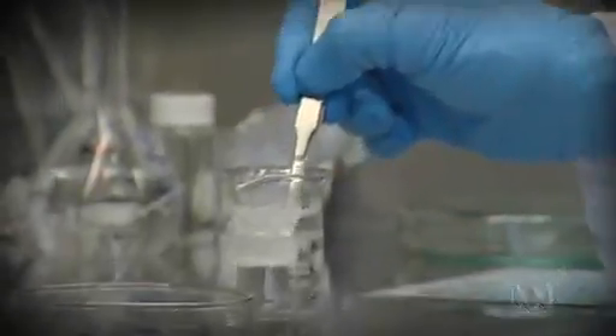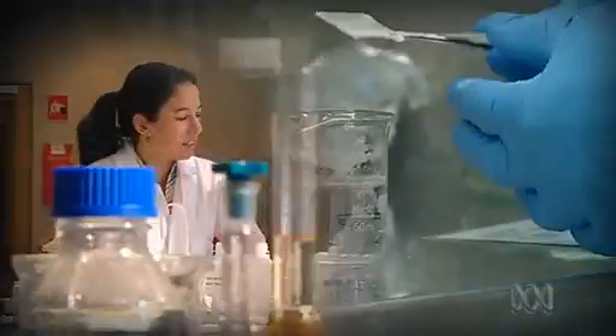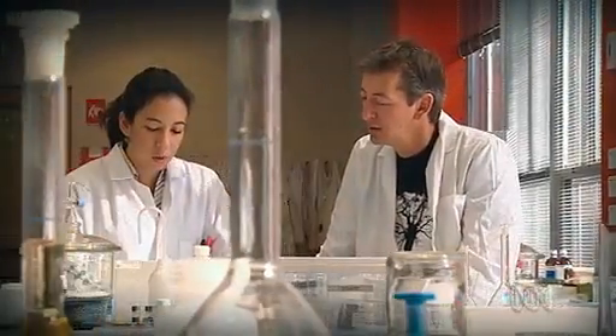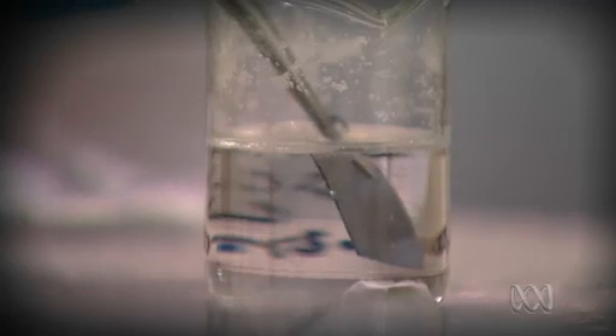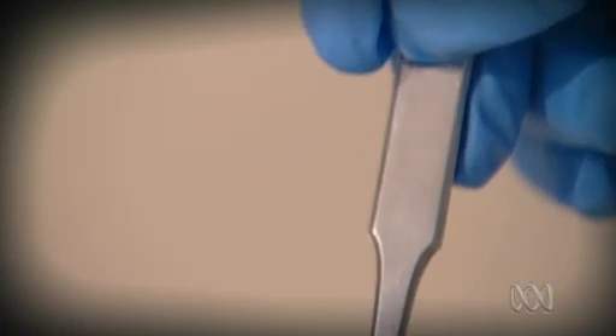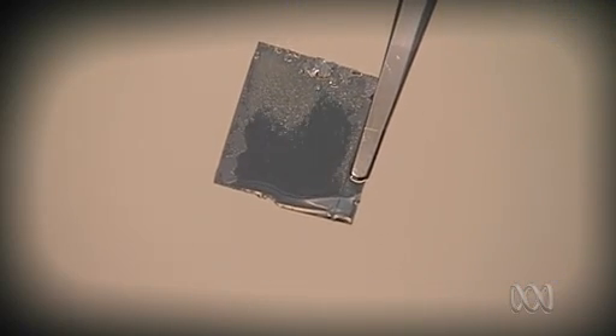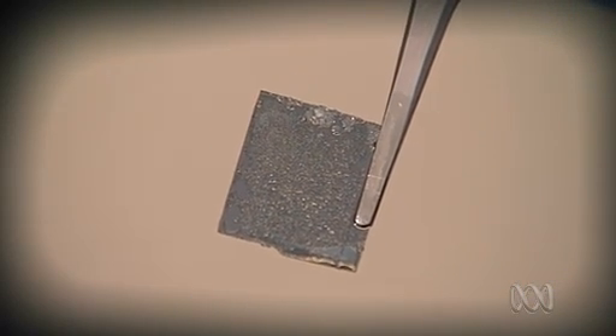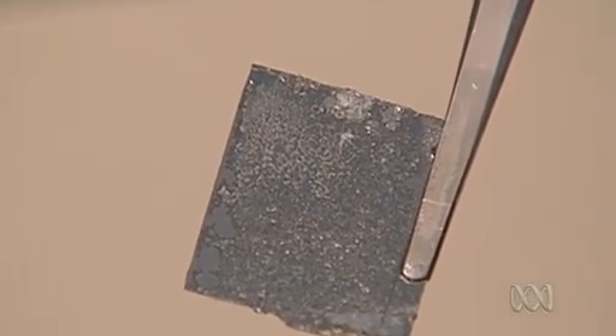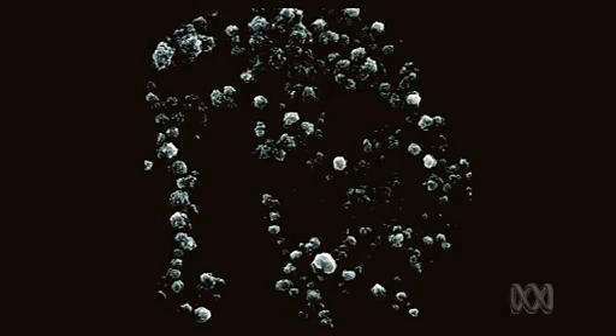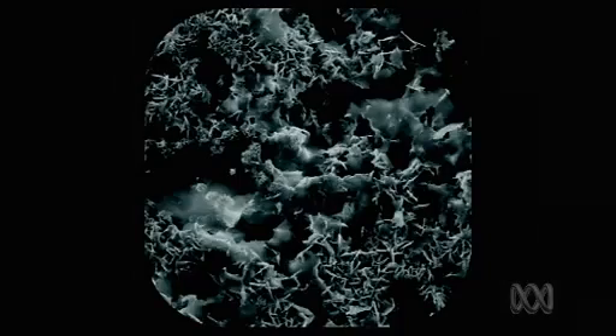Chemists and engineers at Sydney University are looking at cheap and simple ways to imitate the Lotus Effect. I'm immersing this silicon wafer in a solution of stearic acid many times, depositing each time a thin layer of crystals. The crystals are hydrophobic and also very rough. The more crystals, the more air the surface can trap. Dipping 20 times gives Kiara the surface she's after.